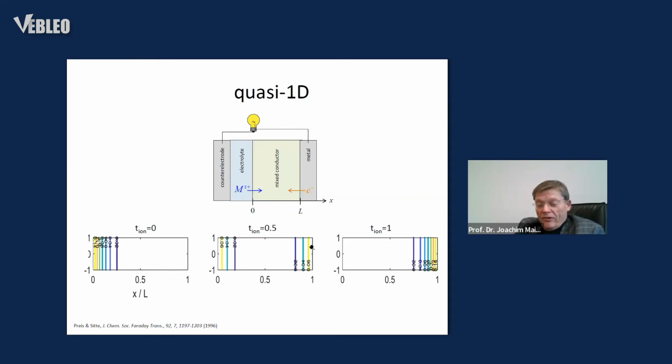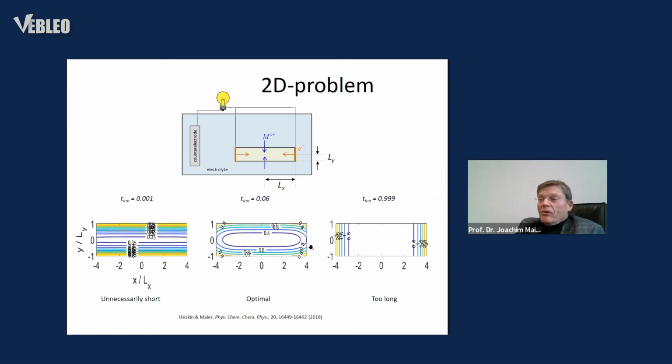So this one-dimensional case is understood. But now we have to deal, because we want to understand the morphology, to higher dimensions. So this is a two-dimensional situation, which already does the job more or less. So here we have the contact to the electrolyte, and the orange one are the contact here to the electron conductor. The same game. If your material is a good electron conductor, obviously everything starts from the ionic contact, so from these long contacts into the interior. It's a very small distance to overcome for this shape. So this is very quick.